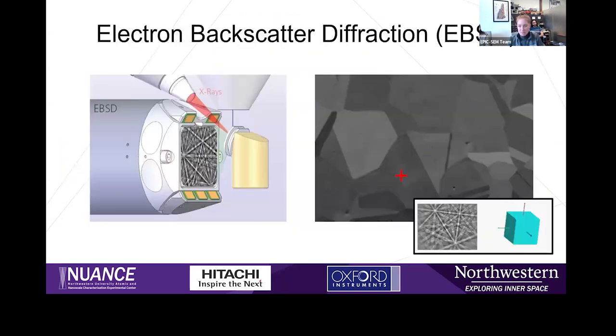Just like other mapping techniques, the beam is rastered across the surface of the sample, and in this specific geometry the sample is tilted towards the EBSD detector surface. The beam interacts with the sample and it diffracts off the surface onto this phosphor screen and projects this Kikuchi pattern. The Kikuchi pattern is analyzed and the information on the crystal structure, phase, and orientation of the grains within the sample is recorded. This red cross right here is just indicating where on the screen the beam is placed and the resulting diffraction pattern from that, and you can see the change in the orientation. And so this is really useful in material science, with a large range of different applications and materials.